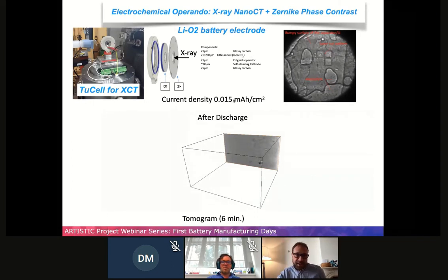To do this experiment, we cut some specific areas in the carbon electrode for 2 reasons. The first one is to clearly identify where the zone of interest is. And the other is to avoid the shadow due to the material during the rotation, when you have a high angle of rotation. To minimize this effect, we just cut some parts on the two sides of the zone.